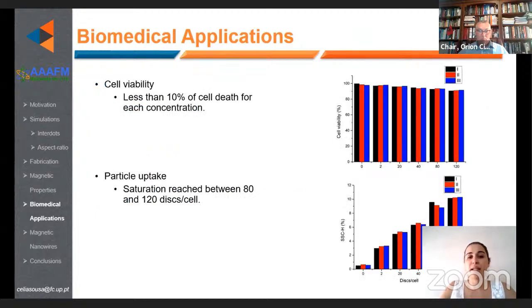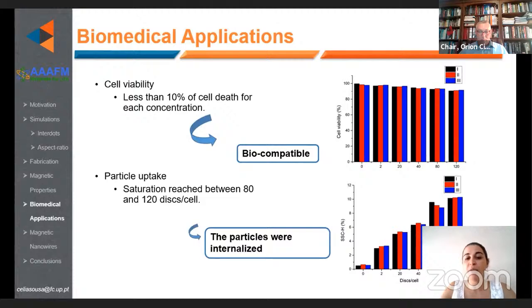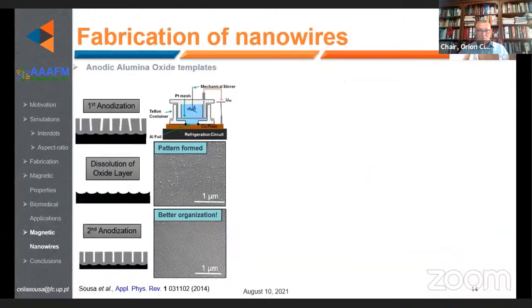So, as we can see here, we achieved a good viability with less than 10% of cell death for concentrations up to 120 nanodiscs per cell, and we also achieved a particle uptake, as we can see here, with a saturation reached between 80 and 120 discs per cell. So we can conclude that our nanodiscs are biocompatible and were also internalized by the cells.